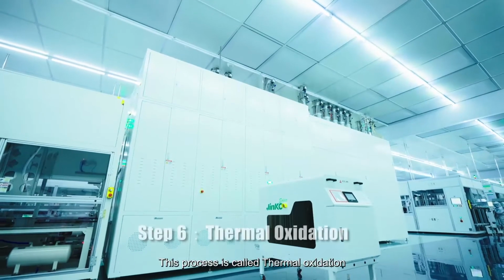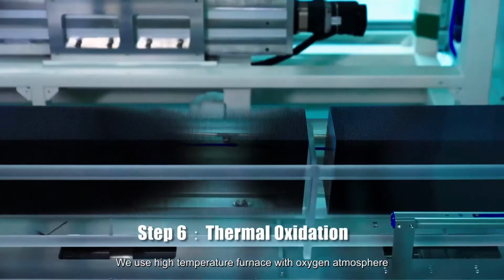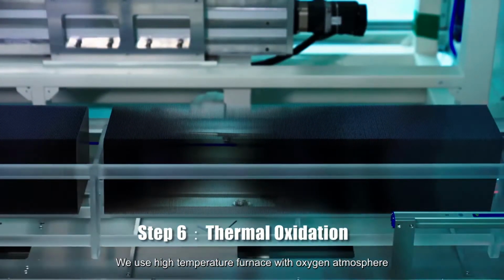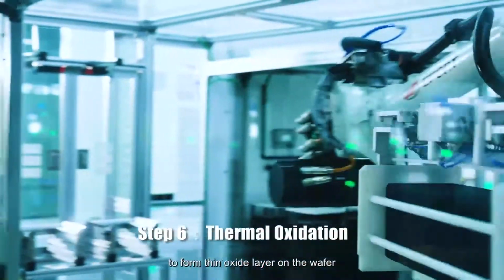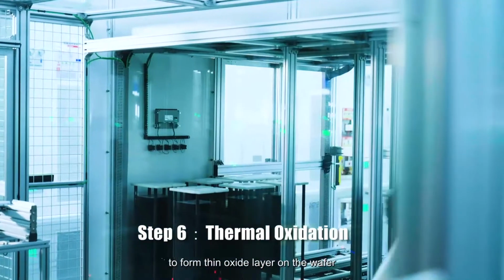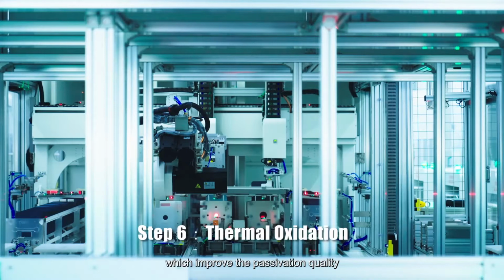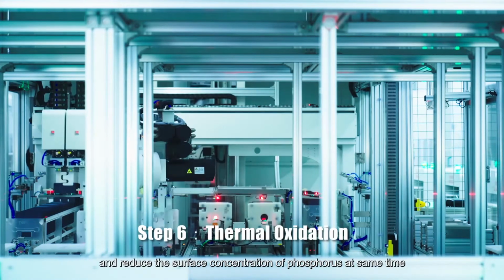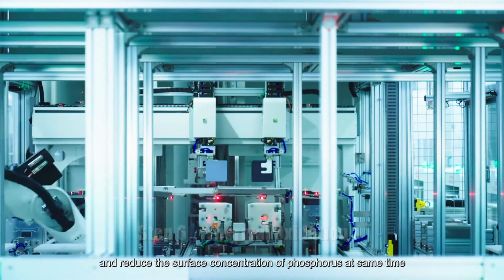This process is called thermal oxidation. We use a high-temperature furnace with oxygen atmosphere to form a thin oxide on the wafer, which improves the passivation quality and reduces the surface concentration of phosphorus at the same time.